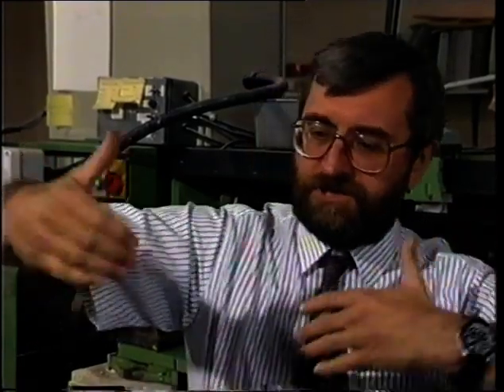If we want high toughness, we actually want the fibre weakly bonded into the matrix, so that when the crack starts to propagate through the material, it sees a weak interface and it turns at right angles and runs along between the fibre and the matrix. And also in the last few seconds as the material starts to fail, what we want is for the fibre to break remote from the crack and for these fibres to be pulled out of each half of the matrix. We call it a shaving brush fracture. But in doing that, we're again using up fracture energy and work of fracture.